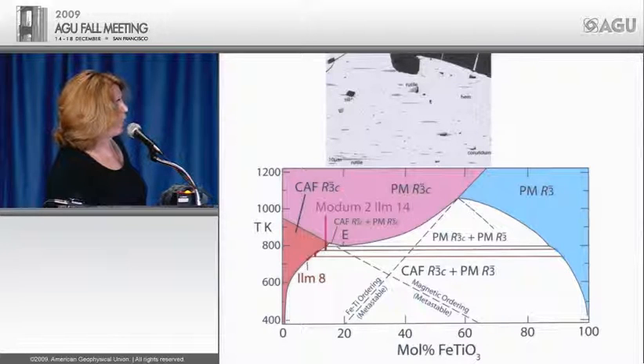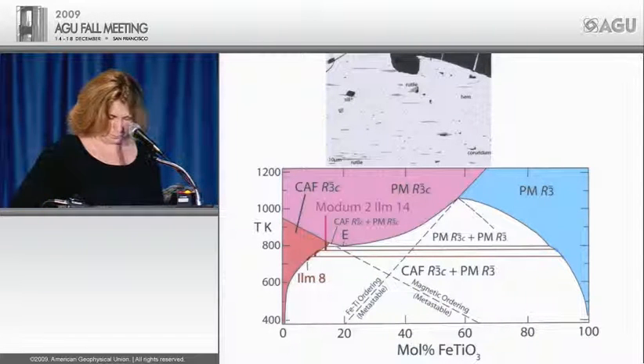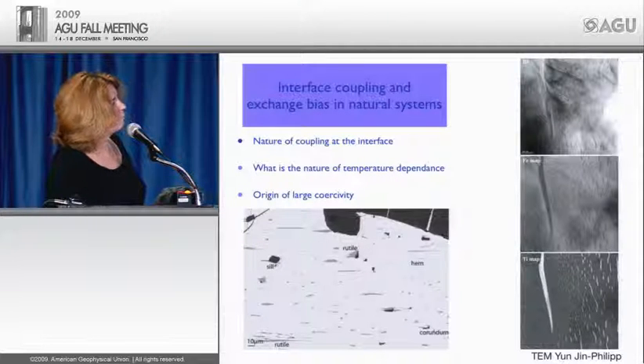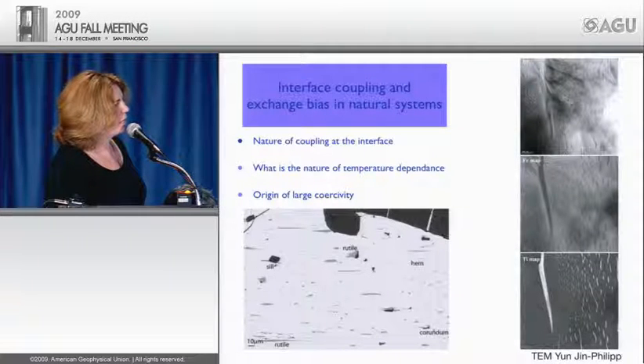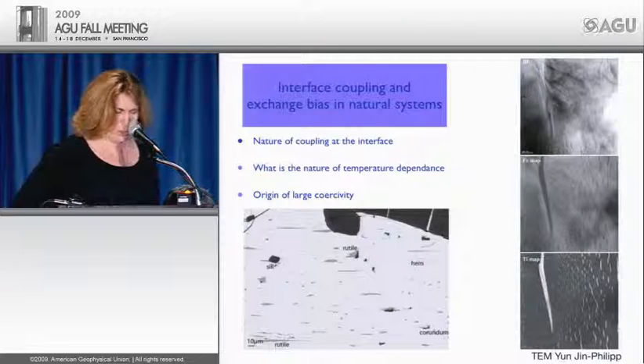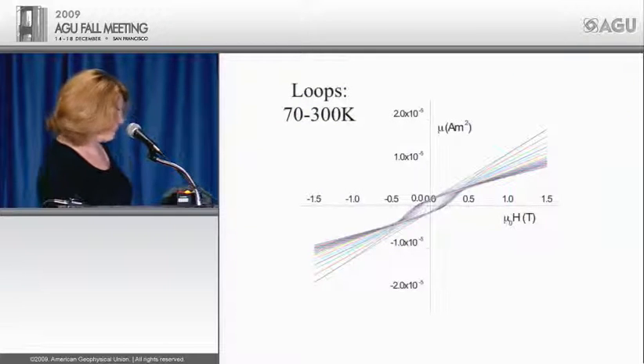And when you look in thin section, the sample here, you just see a beautiful titanohematite. You see some ilmenite. You see rutile, and you see corundum. So we can see here that the Modum sample would have crystallized. It would have started to make ilmenite, and it would have continued possibly to make finer scale ilmenite. Now, this material has very interesting low temperature properties. And what I show you here is the TEM, where we see this nanoscale exsolution. And we have both the iron and titanium maps. And what we find is this exsolution continues down to the subunit cell size.